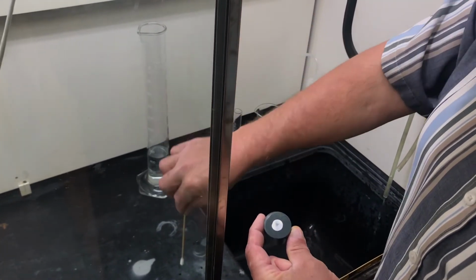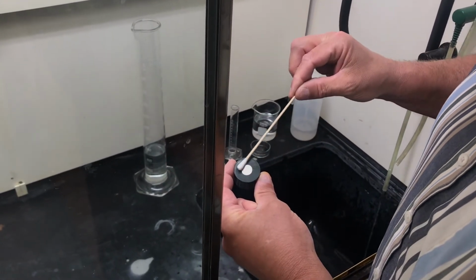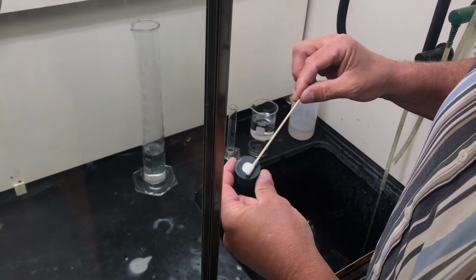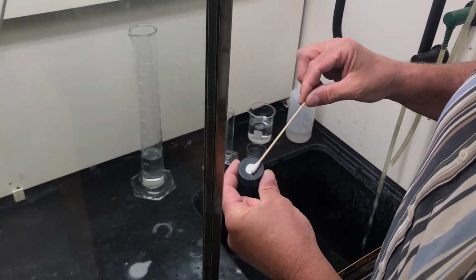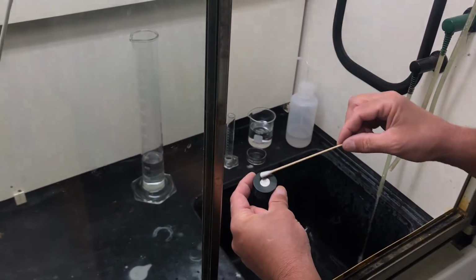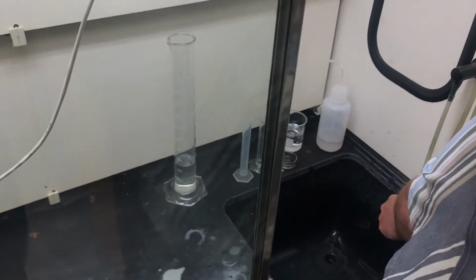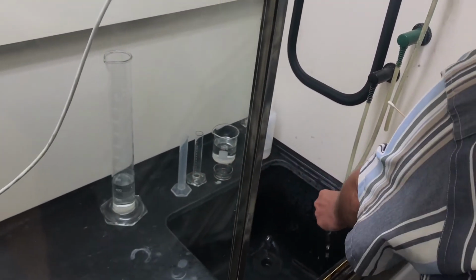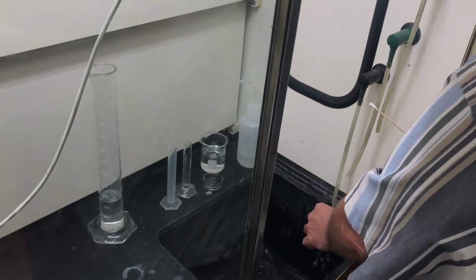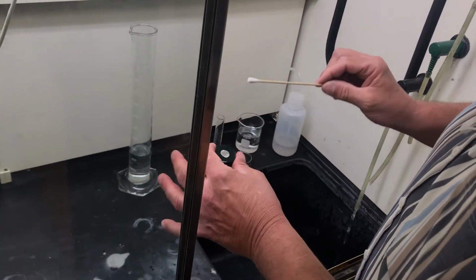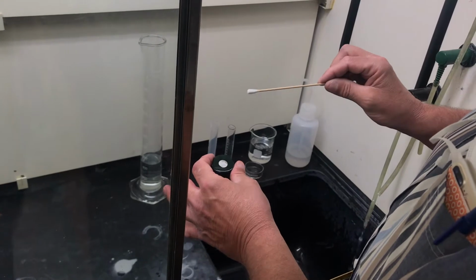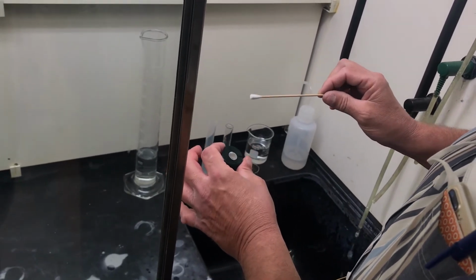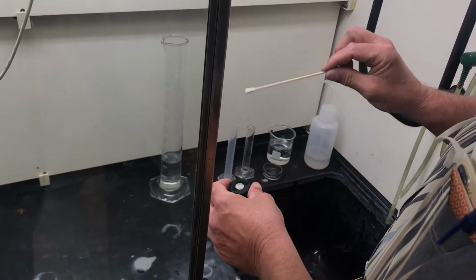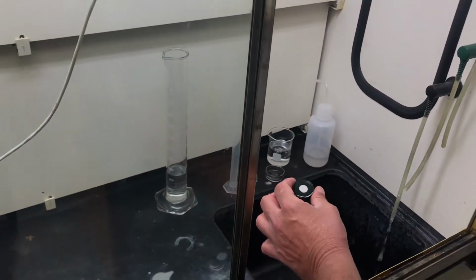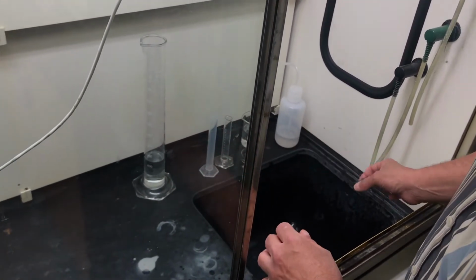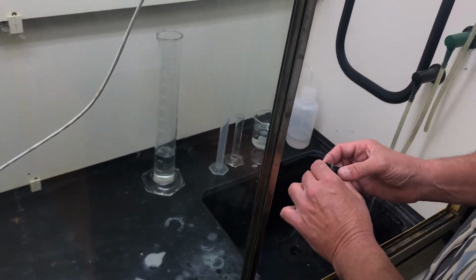So again, dip your swab in the acid, gently go back and forth multiple times, probably 20 to 40 seconds. Start at 20. While you're swabbing, very quickly rinse your sample. Rinse your sample very thoroughly. That will arrest the etching action and clean the sample so that you can handle it with your bare hands. So etch it with acid, throw your swab away. We have plenty more. Rinse the sample.